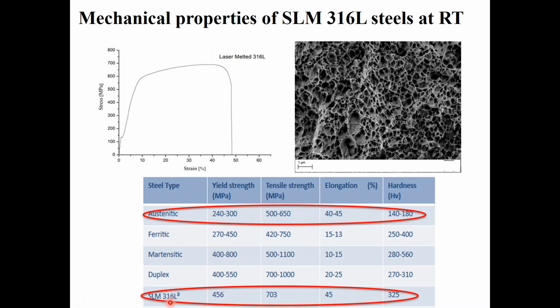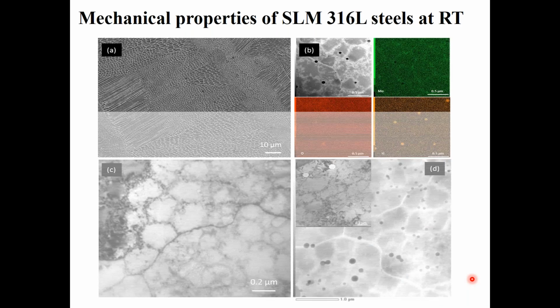And if we compare these properties with the SLM built, which has a hierarchical and heterogeneous microstructure, we can see we have a better yield strength, higher tensile strength, similar elongation, and higher hardness. So for now, I can say we can get a clue that this hierarchical microstructure is different. The chemical composition is the same, so that is contributing towards superior mechanical properties at room temperature. This is the characteristic microstructure, and after deformation, we can actually look through the microscope at how this material is deformed, how the substructure dislocation loops are produced, and how these oxides are contributing towards the high mechanical strength of this material.